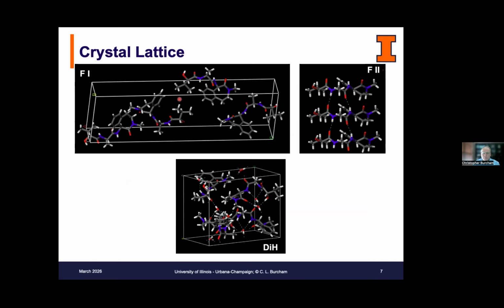crystal lattices. And so here I show the crystal lattice of Form 1. And if you squint hard at this, you can see that the molecule within the lattice is in a conformation where it somewhat wraps around on itself. And if you look at the conformation of Form 2 in the lattice, you see that it's much more planar. It also stacks one above the other, where in Form 1, you're seeing this sort of a head-to-tail stacking arrangement.